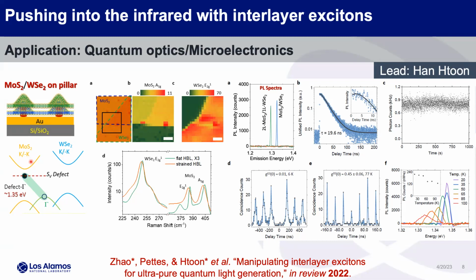But we did this with interlayer excitons because this is air stable, it's MoS2 tungsten selenide. We said this is going to give us a longer lifetime. It's much harder for the excitons that are split between the layers. If you have a hole living here and an electron living here, it's harder to recombine those. So those will have longer lifetimes, making it easier for us to measure, and also relevant to industry because they want things that are more stable and have longer lifetimes.